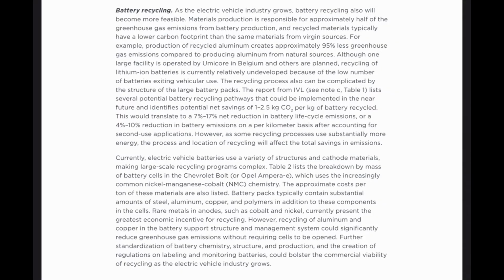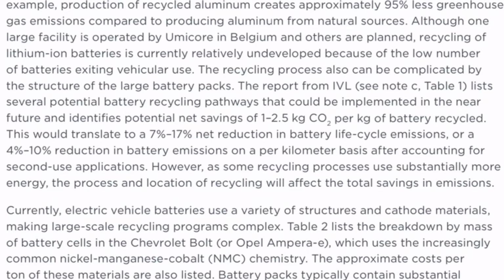They also consider battery recycling, and battery recycling is important because if they can repurpose the battery materials for other needs, they can further cut down 1 to 2.5 kilograms of CO2 per kilogram mass of the battery. That can account between 4 to 10% of reduction on a per kilometer basis and a 7 to 17% reduction overall in life cycle emissions.